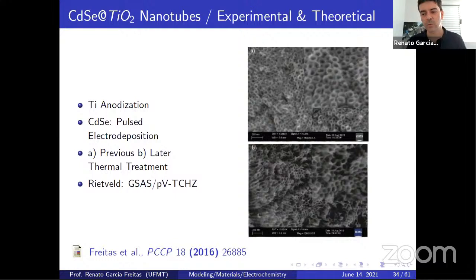And the question was, when to do that? Before thermal treatment, or after thermal treatment? Previously, we obtained the titanium nanotube, calcinated, and electrodeposited cadmium selenide, or later, we obtained it, calcinated, and soon after electrodeposited cadmium selenide. And we also performed Rietveld refinement, the Thompson-Cox-Hastings function, to obtain the fit. The most important part is the tube, for sure. Take a look here. The tube is opened. You see here, the tube is opened, even for the one previously calcinated, or the one we electrodeposited and then calcinated. And it's opened.